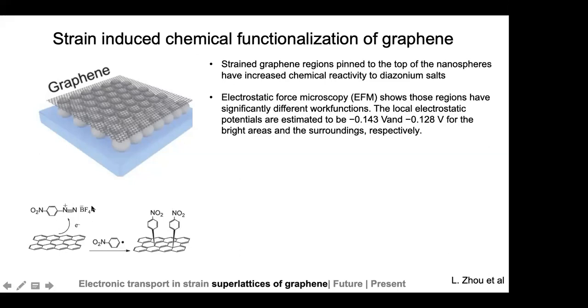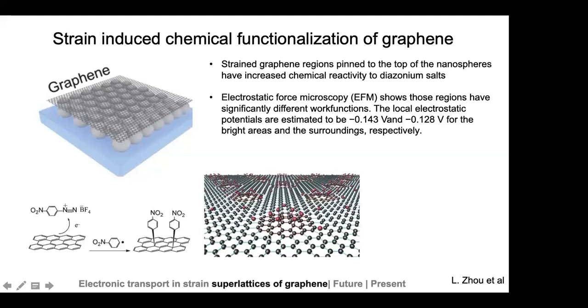So when diazonium molecules react with graphene, these nitrobenzene groups are expected to adhere to the surface of graphene. And what was observed was, if you have graphene on top of such nanospheres, then the nitrobenzene groups preferentially adhere to those regions which were on top of the nanospheres.